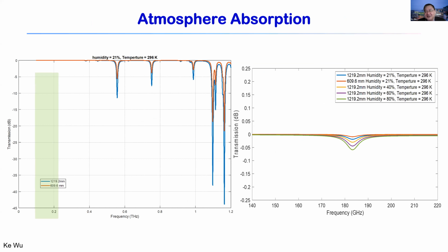I just show you here, for example, the 180 gigahertz range, a little bit more than 180 gigahertz. You can see that with different humidity, you have different absorptions for the transmission here. That's why it's very delicate to make a measurement. And at different frequencies, even for a given temperature and humidity, you also have very strong absorption due to oxygen and so on. Those are the natural absorptions, which are affected by both the oxygen and the weather conditions.